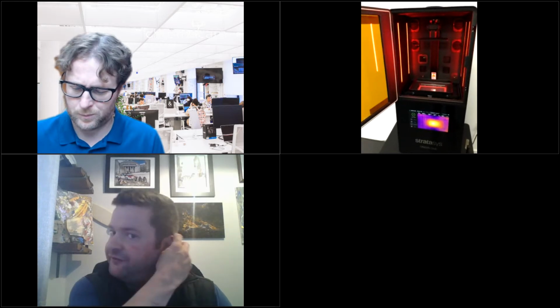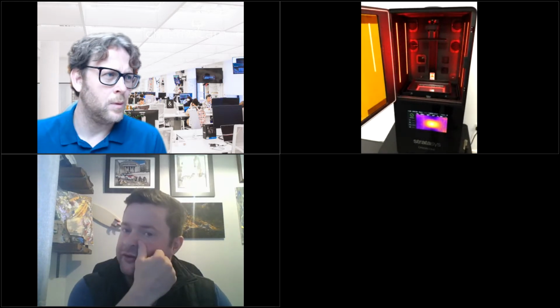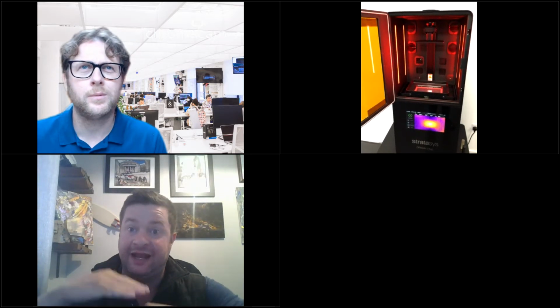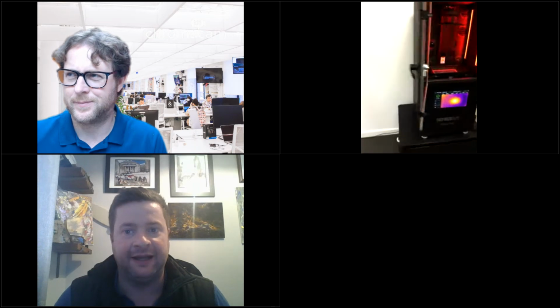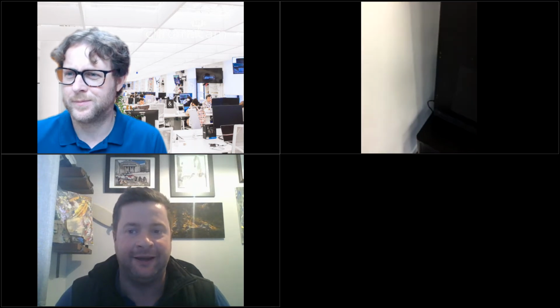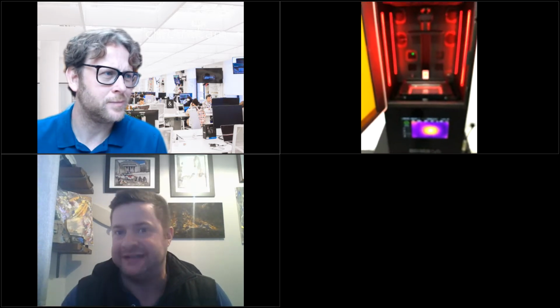The image is showing the infrared camera. So we're monitoring the oven temperature, and we're monitoring the exothermic reaction per layer when it cures. We're also monitoring the temperature of the material, because obviously viscosity changes depending on the cross-sectional area that you're exposing. So there's a lot of sensors in there, a lot of software in there, and it's significantly an improvement over others out there on repeatability and reliability. Honestly, it's mostly down to software and sensors and what we're looking at as well.